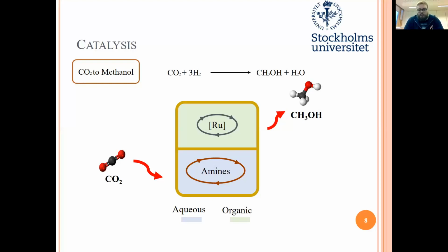And the function of the aqueous solution is to sequester the CO2. Aminated solutions are a very well-known process to capture CO2. If we combine this capturing with this homogeneous catalyst, we obtain the synthesis of methanol through hydrogenation reactions. So what we're trying to do is heterogenize this system, to make it a heterogeneous system in which the catalyst would be in a different phase from the CO2. In our case, it would be a solid phase, and the CO2 is in a gas phase.